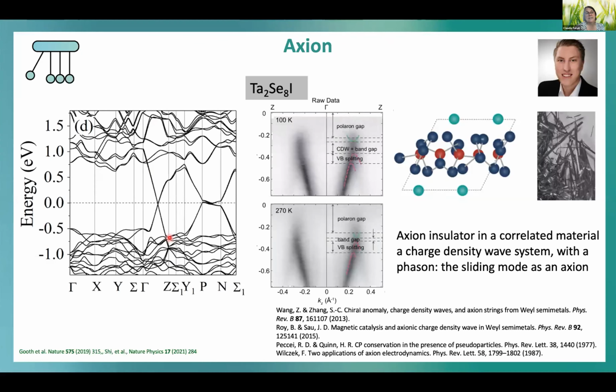If you see here, it looks nearly like graphene, but the interesting thing is that this crossing point in the band structure is not at the high symmetry point, which is obviously visible. So we grew single crystals, but we were surprised that they were in some sense semiconducting. By looking into angle-resolved photoemission very carefully, we saw that the system has a charge density wave gap, and this was in agreement with the literature at this time.